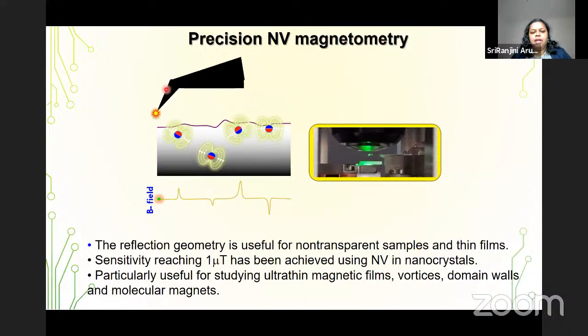You all know about the AFM, in which we have a cantilever, and on the tip we attach the diamond, and as we scan, as they are at different distances from the surface, they can sense a different magnetic field. They can be sensed very precisely up to 1 microtesla using the NV diamond in nanocrystals. This is very important and useful in studying ultra thin magnetic films, vortices, domain walls, and molecular magnets.